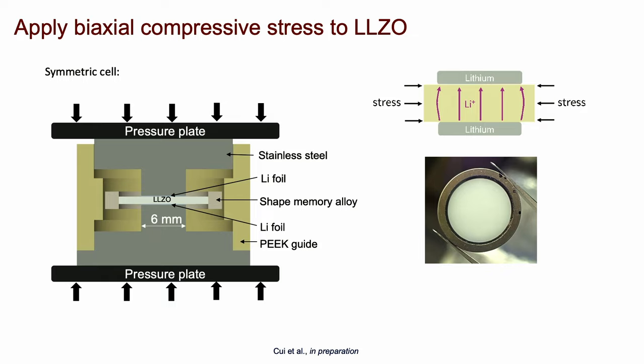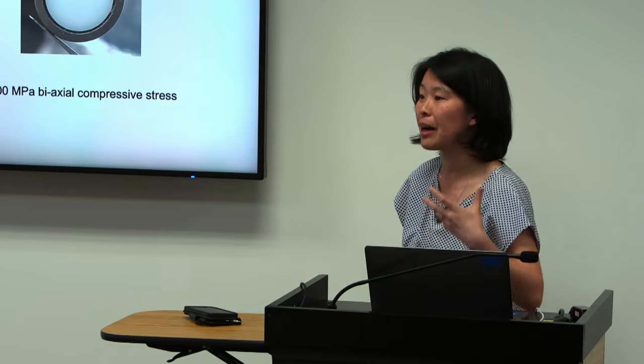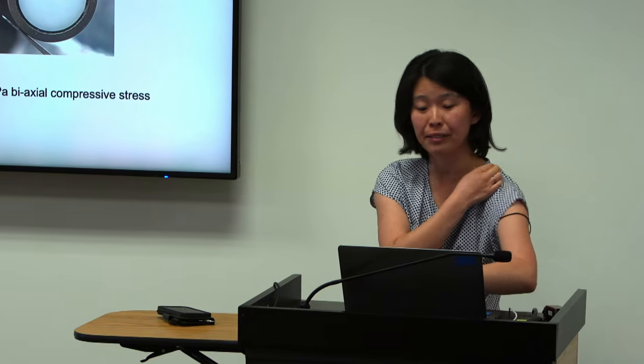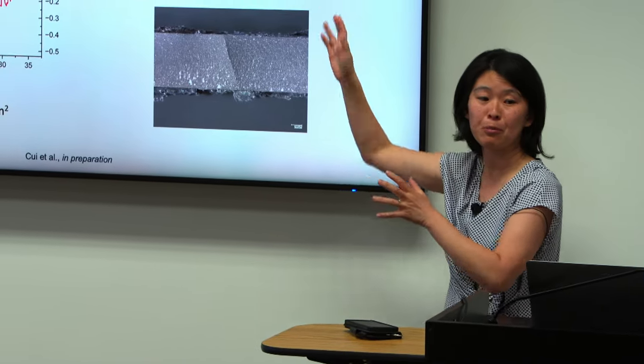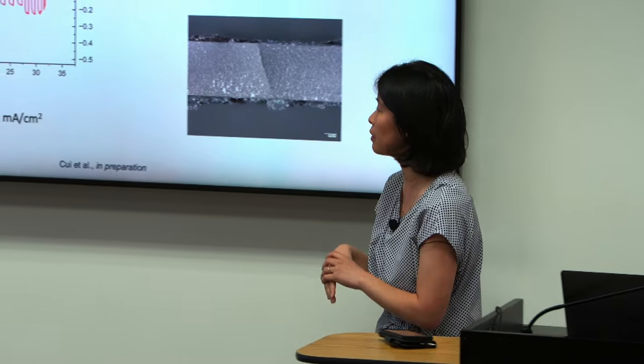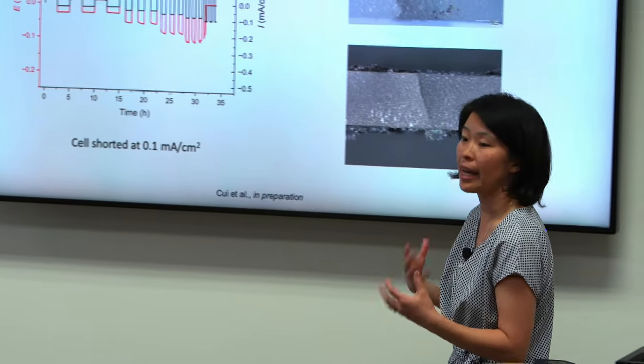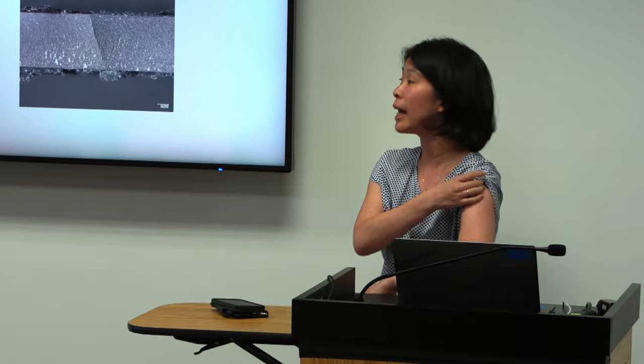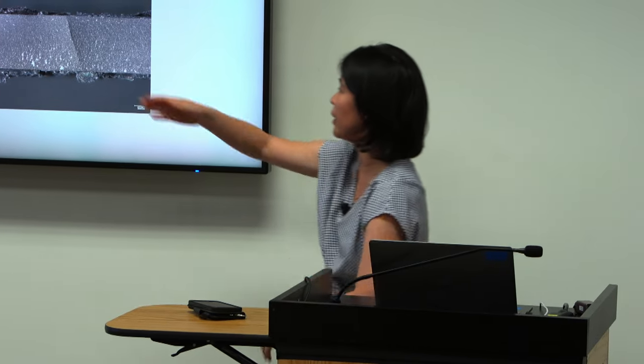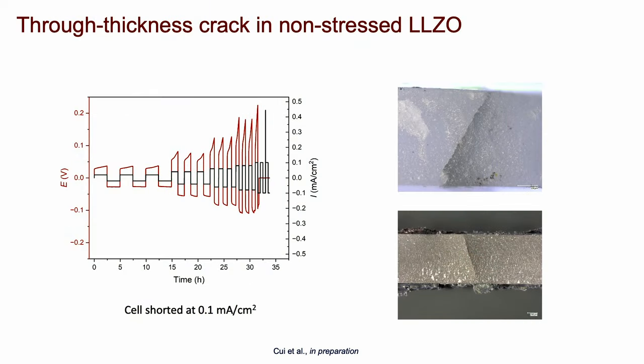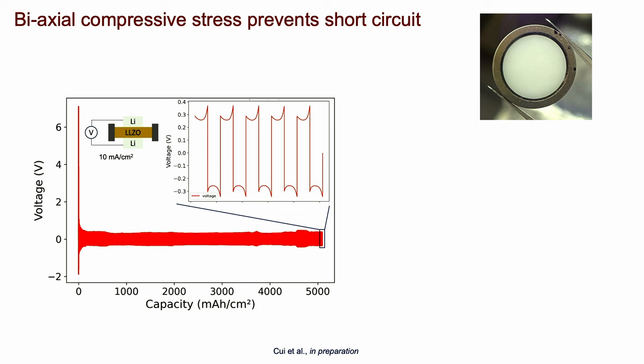The application of stress worked, and this leads to about 400 megapascals, which is quite high, of compressive stress in our material. This is the control sample before we applied the stress, and it's quite typical in the field. After maybe 10 or so, possibly up to tens of cycles, the cell will break, and then we see the formation of dendrites, these diagonal structures forming across the LLZO. But after we add this biaxial compressive stress, where we have this ring around the LLZO, we see that the cell lasts much, much longer.